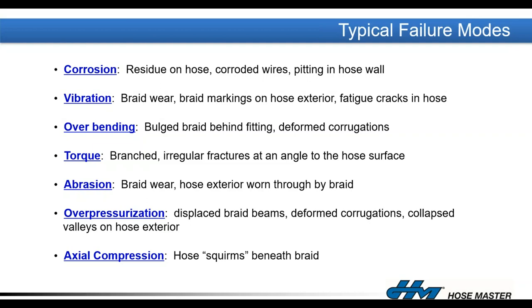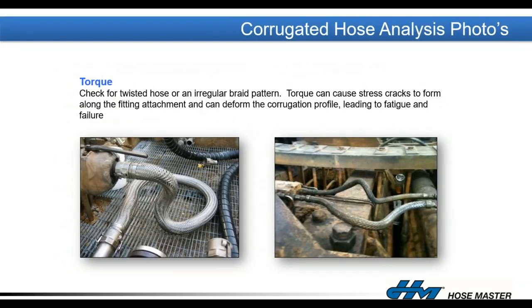Signs of overbending of the assembly are typically evidenced by the braid bulging out directly behind that fitting. That's a clear indicator in the field that the hose is being bent beyond its design. Any signs of twisting the hose assembly, torque, abrasion, external wear showing braid wear. If you see any jagged braid wires sticking out from the assembly, that external abrasion has caused those braid wires to come apart, and now that hose's working pressure has been compromised. An external guard or protection would help that. Signs of overpressurization: the corrugations start to deform and inflate, and axial compression where the hose will squirm. Some of these failure modes can look very similar to each other, and that's the value that our lab brings.